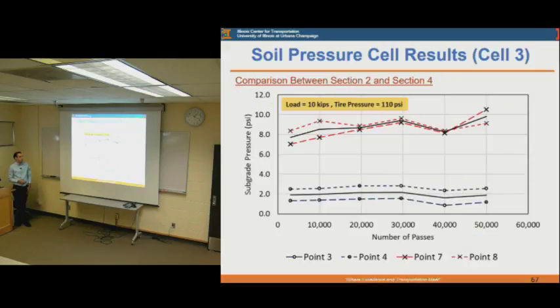And then this is a summary of the results from the 2 test sections in cell 3, so 2 and 4, which is the test section with the inverted pavement and then the control test section. So for the inverted pavement test section, we're also in the same range of 2 psi subgrade pressure on top of the subgrade, which is low.